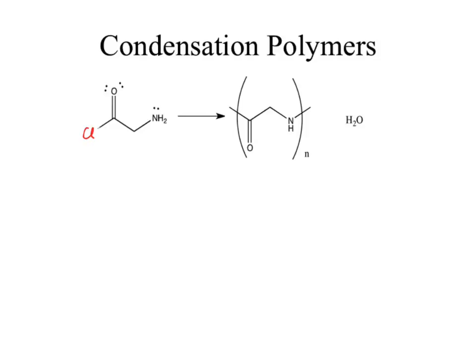I heard a couple suggestions on making it under acidic conditions. If it's under acidic conditions, what happens to our nucleophile? I still lose the nucleophile. I may still have the electrophile, but I lose the nucleophile. That gets rid of half my puzzle. So really the only way I can get this one to work is by getting rid of that acid functionality through two possible methods. I can either turn it into the ester, which I had not even considered, so good job. Or we could turn it into the acid chloride.